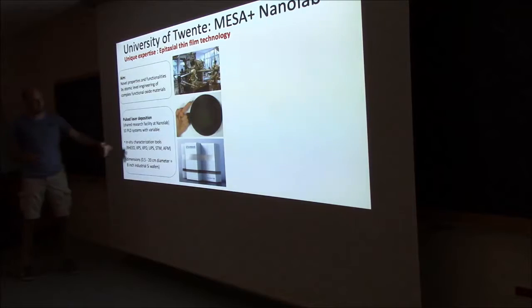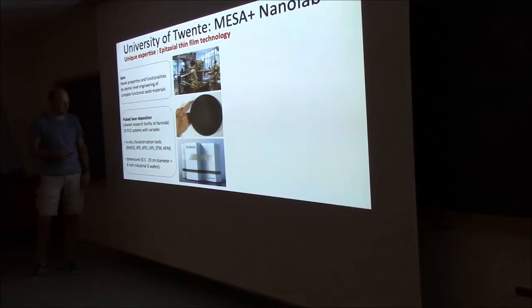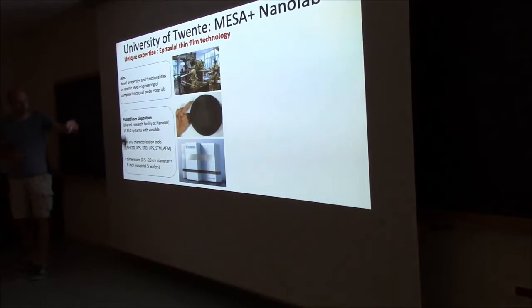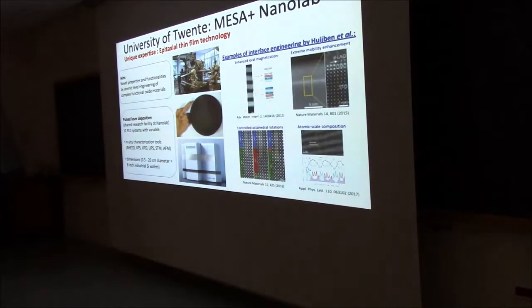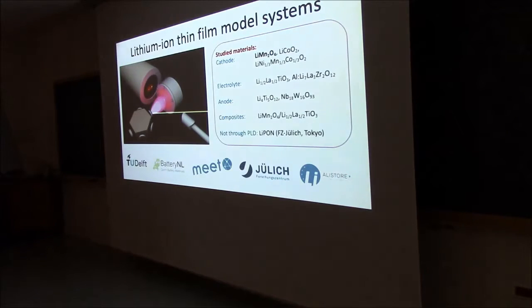So I've shown you 2 days ago that we do pulsed laser deposition in our group, going from something which is small to wafers. We've used it for a long time to study all kinds of materials with interesting magnetic and electrical properties, and we still do this heavily. But we also started doing this for lithium-containing materials. And here you can see several of them: cathode, anode, or even electrolyte, composites between them, and in some collaboration we also study some amorphous materials.